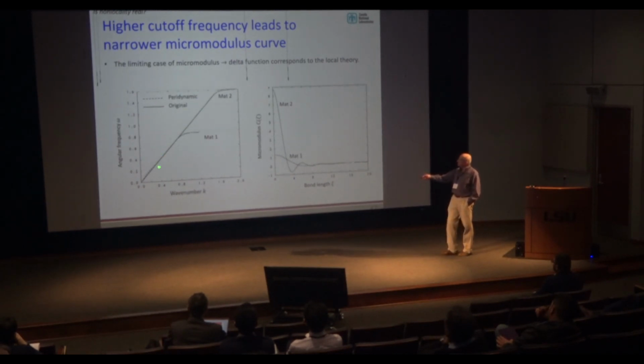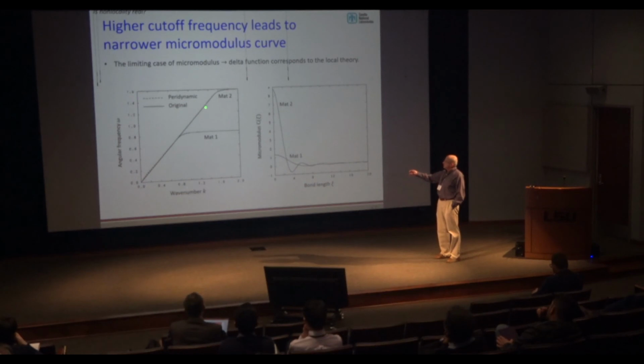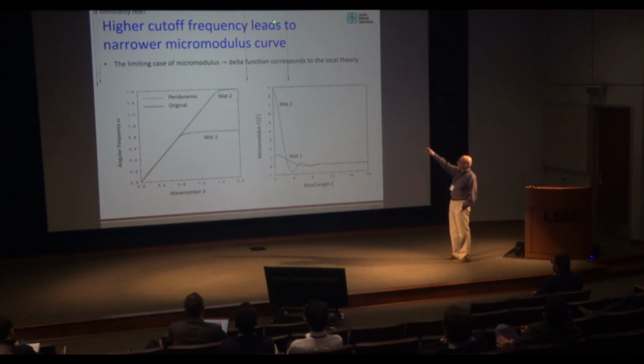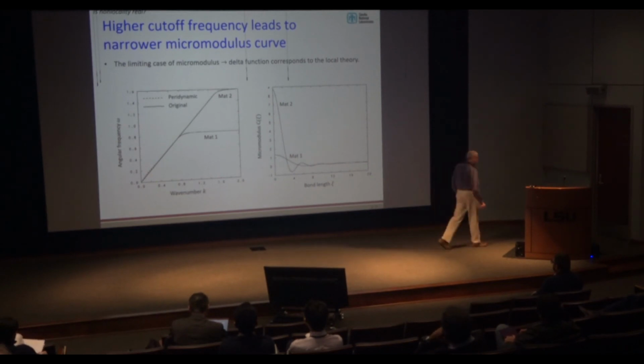So you can reproduce a given dispersion curve just by inverting the Fourier transform of given experimental data from the dispersion curve. The higher the cutoff frequency, the skinnier the micromodulus function after you do this conversion process. So in the limit where this cutoff is very large, this micromodulus starts to look like a delta function, which corresponds to the local limit of the non-local PDEs.